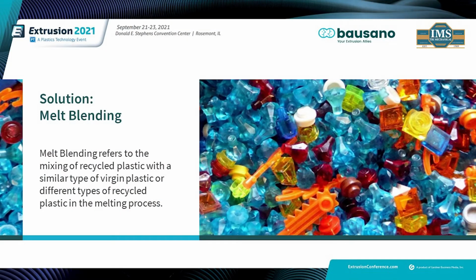The melt blending technique is best when doing post-industrial scrap, basically due to the clear separation of the materials, and you also have less contamination in post-industrial scrap, and the low level of contamination present. Researchers mixed HDPE, LDPE, and PP with their individual virgin materials and tested their tensile strength. The results showed tensile strength of recycled plastics can effectively be improved by melt blending.